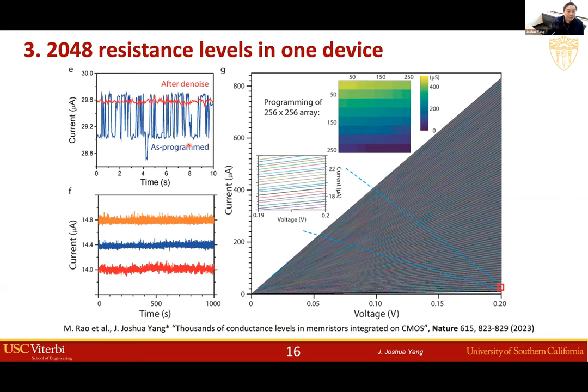So we managed to actually understand what's going on with the noise and develop a protocol to denoise the device. And after denoising, you can see the resistance level become very stable. And then neighboring resistance levels are very close to each other and still distinguishable. So with that, we managed to get over 2048 resistance levels, which is equivalent to 11 bit in the device. They're actually fabricated in the fab.